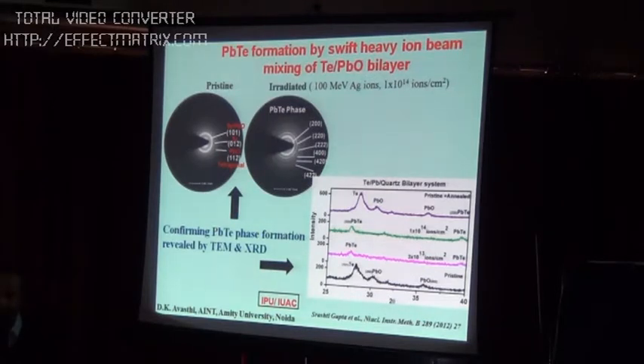But when I irradiate, then you can see you have lead telluride here, complete lead telluride. So this complete thing had converted into lead telluride, and this is the proof of that. This is the transmission electron microscopy selected area diffraction pattern. You get all the rings due to lead telluride formation. So this is the confirmation from X-ray diffraction and transmission electron microscopy. So here what I have shown is that you are able to get lead telluride by ion beam irradiation, by ion beam mixing process.